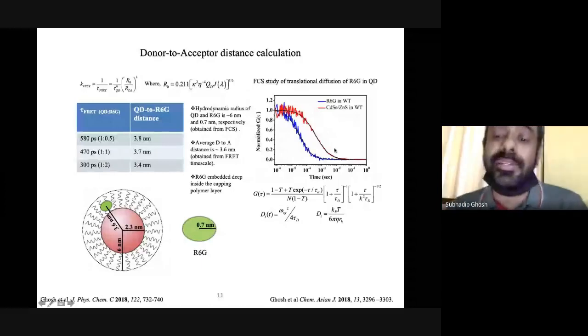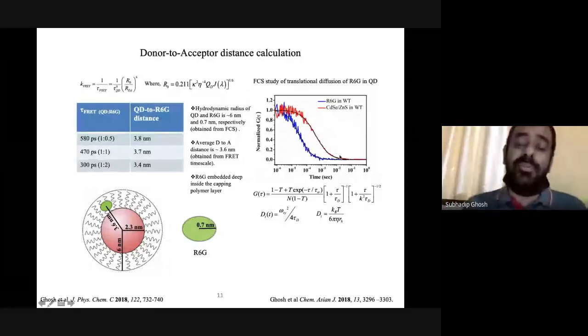And from this curve, after treatment, we can get the translational diffusion time of the molecule. Now using the Stokes equation, we can get the diffusion constant, and from there we can get the size of the molecule. And here we found the hydrodynamic size to be 6 nanometers. Hydrodynamic means the entire molecule, but the semiconductor portion obtained from the time measurement is around 5 nanometers. So the length of the capping agent is around 1 nanometer.